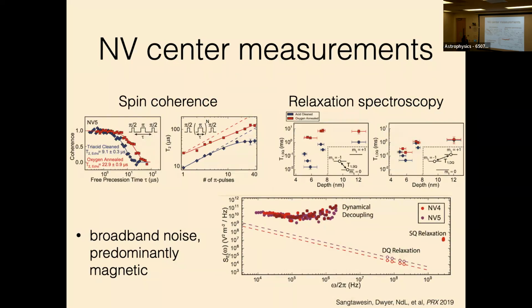So if we just do, say, a Hahn echo sequence to look at the spin coherence time, this is now one NV center where we can find an individual NV, do this last oxygen annealing, and go back to it. And we can see that the coherence time is extended by a little bit over a factor of 2.